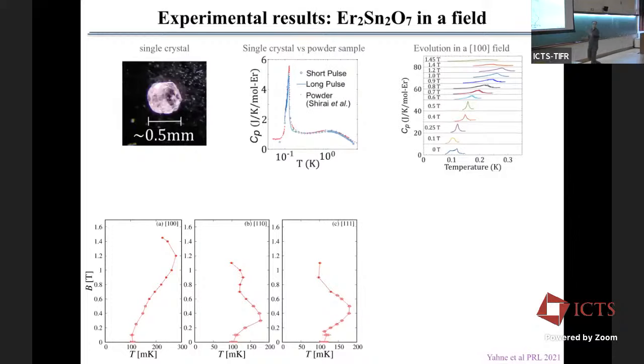So this is the phase diagram that you obtain. And so the only point to remember here is that we have a frustrated system pyrochlore. We have put a magnetic field in three different directions, 100, 110, and 111. And in every case, we see a reentrance. So as we increase the magnetic field, first direction goes up, then it goes down. Here it goes up twice, and here it goes up once again. But every time we have reentrance.